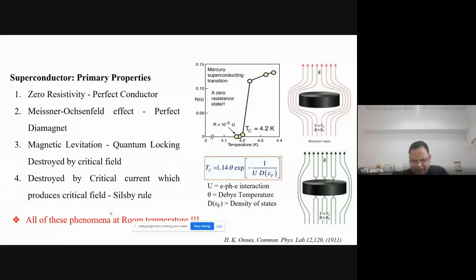cannot be beyond a certain limit, because there comes an interacting potential between the carriers also. So even within the BCS framework, you have to see that lighter elements are used, theta D is higher, electron-phonon interaction is maximum. At the same time, density of states must be in a very clear-cut domain, so that it can get the highest TC with strong correlations and all that.